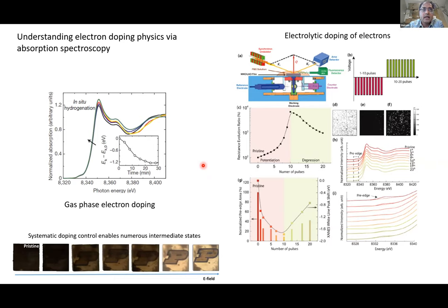In terms of practical, application-driven differences, we found that lithium, for example, is very picky in terms of the electrodes that you can use for introducing it. Similarly for sodium. Many of these experiments we did using liquids because we wanted to just show the proof of concept. For lithium, we use lithium cobalt oxide, but still you need to use some sort of polymer gate on top of that. So the overall stack structure is more complicated, based on the experiments we did for lithium, sodium and magnesium.